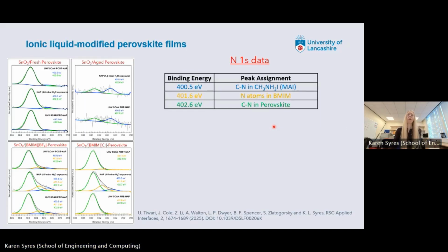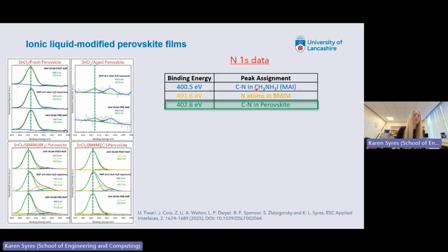Then we're looking at the ones with the ionic liquid as well. Here we're looking at the nitrogen atoms. And again, the green peak is the one that we want. This is the CN bond in the perovskite structure. We can see with the fresh perovskite, we've got lots of that, whereas with the aged perovskite, there's very little of that. In fact, most of the nitrogen has just completely gone from the aged perovskite.